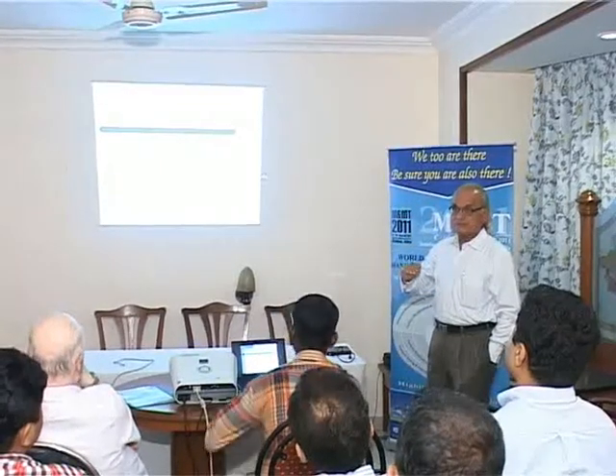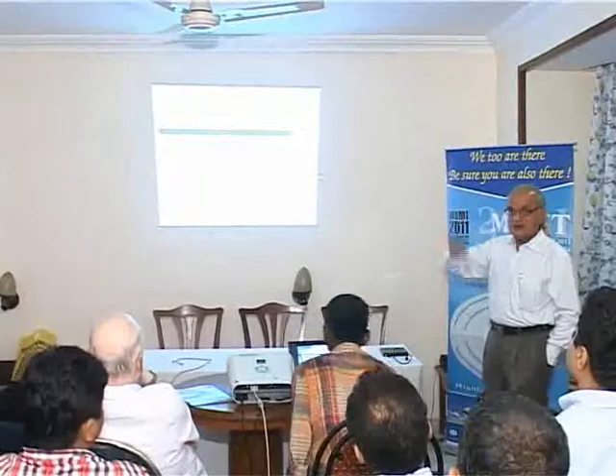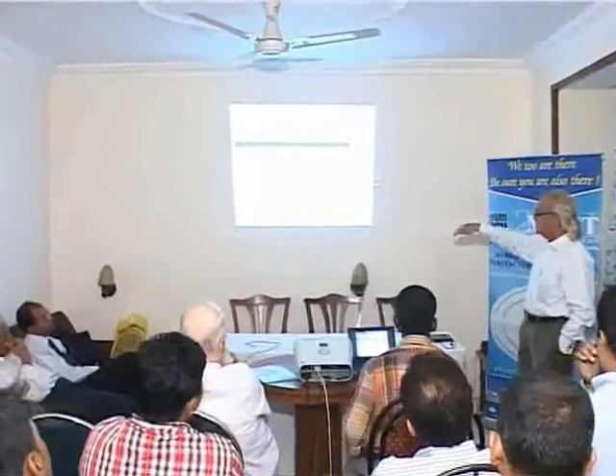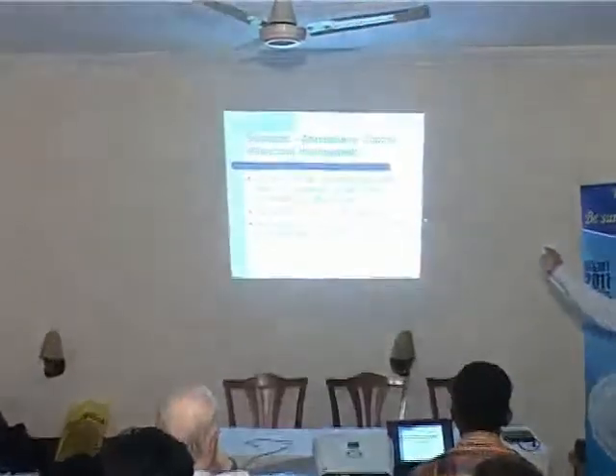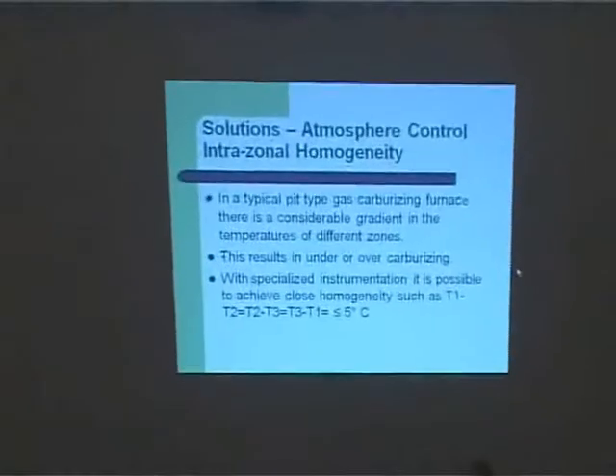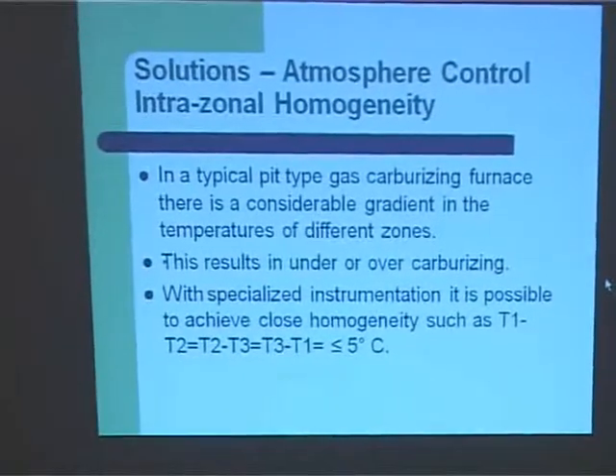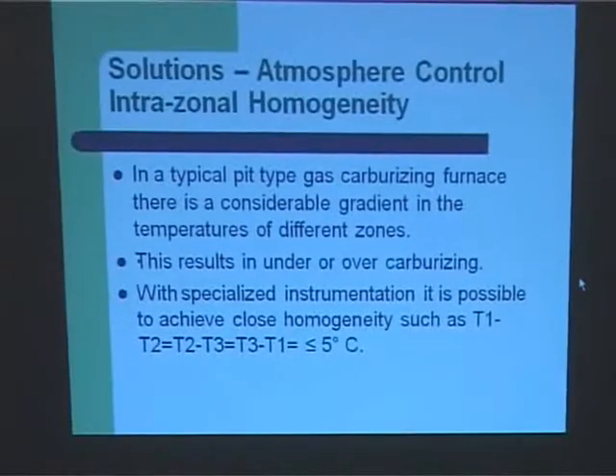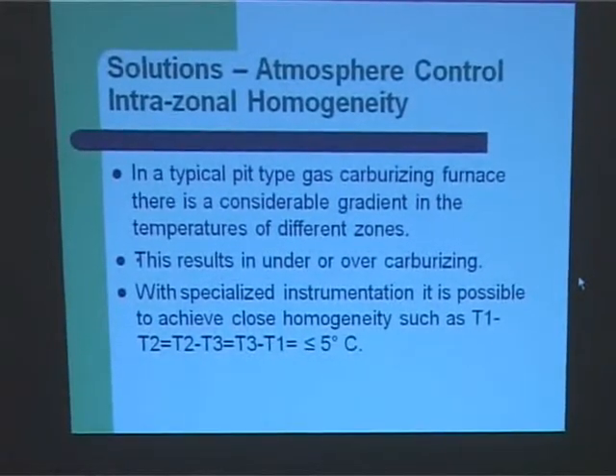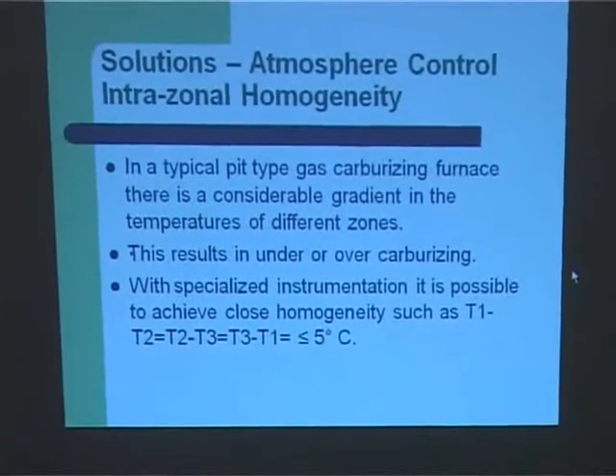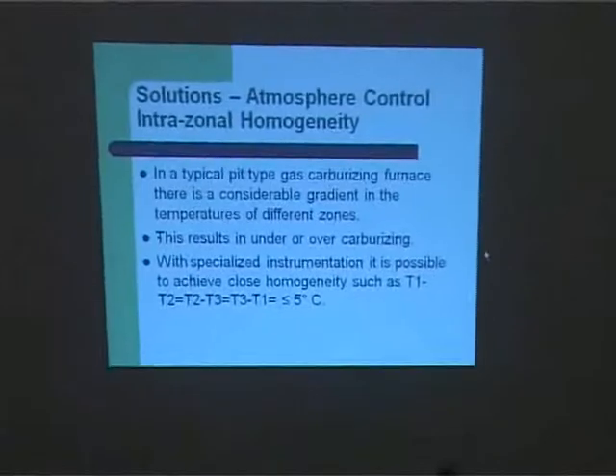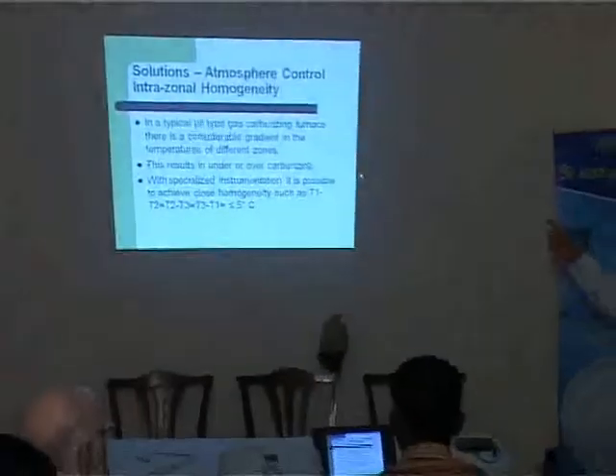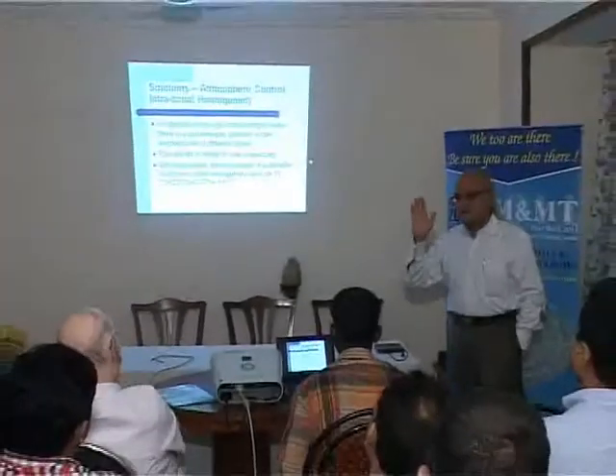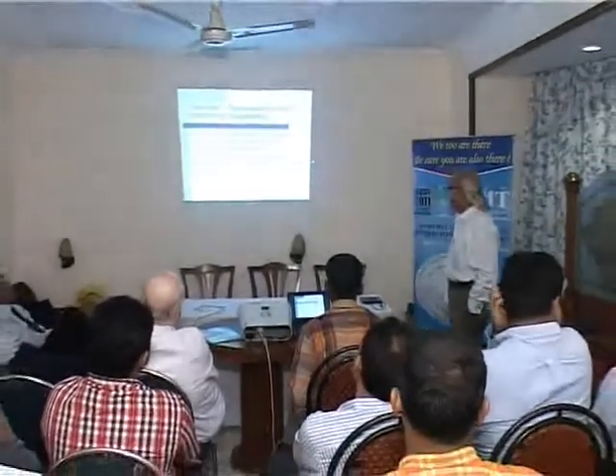A typical 3-zone temperature control: top, middle and bottom. How do you regulate this so that all of them are within a narrow band, say T1 minus T2 is equal to T2 minus T3 is equal to T3 minus T1, equal to or less than 5 degrees? That kind of achievement is possible with proper sensors and proper controllers. This is called intrazonal homogeneity. Homogeneity of temperature, because the carburizing atmosphere diffuses because of the fan there. But heat, because of convection, does not really travel that much. And at this temperature, about 920 degrees, the bulk of the heat is by radiation, don't forget it. Next.